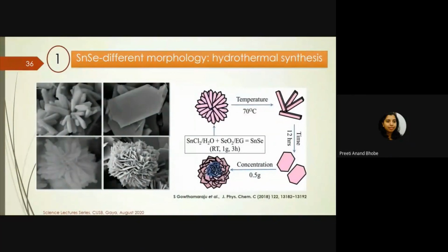Now comes the first part, which I said I would come to at the end, of getting nanostructures of SnSe. Of course, one can get beautiful morphology by hydrothermal synthesis, as those who work in the nano field will know. You try to make materials using hydrothermal synthesis, and one can get beautiful morphologies of rods, flakes, and flowers, and that's what we got for the SnSe that we prepared using the hydrothermal method. We change the temperatures, the concentrations and the time of the reaction, and depending upon all these factors, we could control what kind of particles we get.